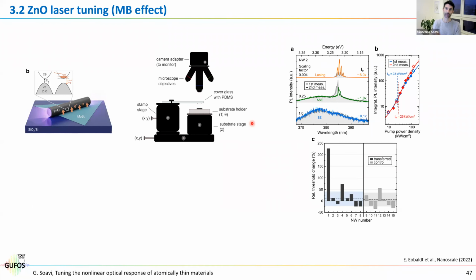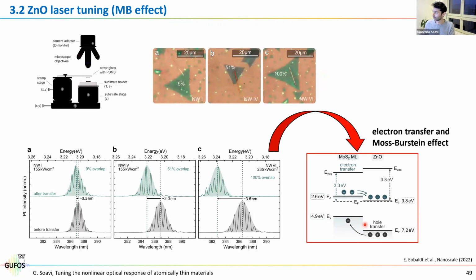We are also thinking of making the contacts by graphite first. The problem is that zinc oxide has a huge band gap. I mean, you can see it from here. The emission is at 380 nanometers, so it's almost 3 electron volt or more than 3 electron volt gap. So you can see here.